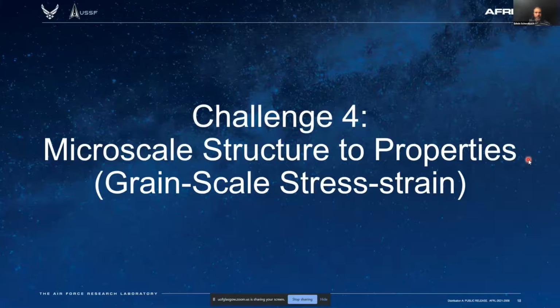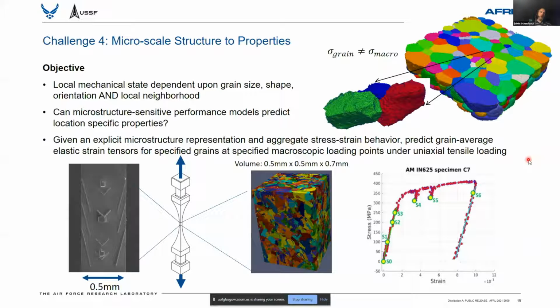Our final challenge, checking the clock here, number 4, was again sticking with structure to properties, but now moving down to very fine scales, grain scales. Here we're really looking at the response of a particular grain in the material to aggregate loading. So in this experiment, we took a tensile bar that was designed to go into a high energy diffraction microscopy setup at Argonne National Lab in the synchrotron at the APS. This is a specimen that has a relatively small gauge volume, about 0.5 millimeter by 0.5 millimeter by roughly a millimeter in length.